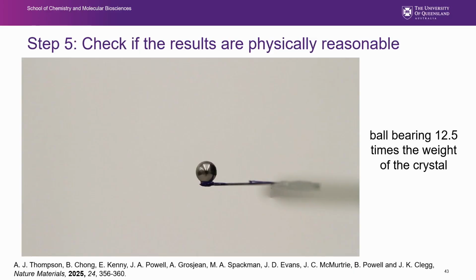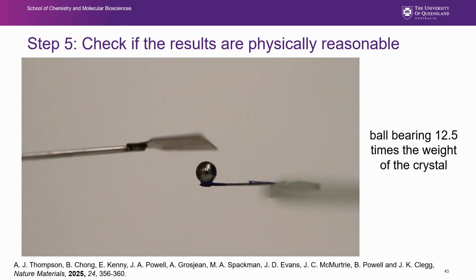So the next thing, and probably the most important, is we need to check that the results are physically reasonable. And to do that, we decided to have a lot of fun. We decided that we needed to try and make some cantilevers, and we should take our crystals, here's a nice crystal, stick ball bearings on them and see if they could spring back up against applying a force. And when you watch each of these ones, starting with just 12.5 times the weight of the crystal, just check if the crystal goes above the neutral position. And you should see that it does.